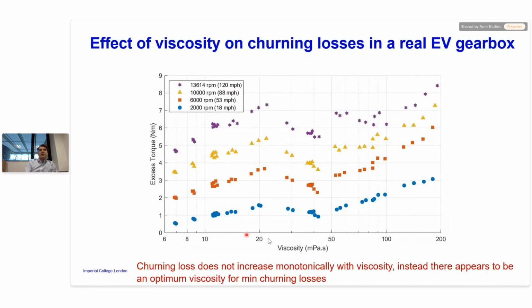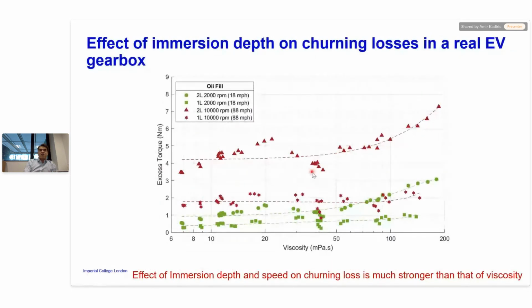You can see that initially the torque goes up with viscosity, and then it drops, and then it goes up again. It's not the same place in terms of viscosity, it's not the same speed and so on, but the fact that you see the drop means that generally the trends are the same. In the same gear unit, Alex also varied the immersion depth. And this is important because you find that the biggest effect on gear churning losses by far is the immersion depth, not the viscosity. So compare either the red or the green curve. Let's look at the red curves. They are at the same speed of 88 miles per hour vehicle speed, 10,000 RPM gearbox speed.